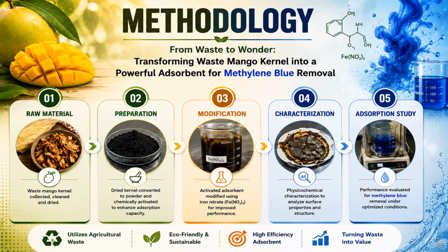Let us now sneak into the methodology. Waste mango kernel was collected, cleaned and dried. Later, it was ground and sieved through a 500 micrometer mesh and dried at 60 degrees Celsius for 1 day. Then, the powder was heated at 500 degrees Celsius for only 30 minutes, yielding the biochar. To prepare iron-decorated biochar, the prepared biochar was mixed with iron nitrate in a 1:2 mass ratio, and then, after the addition of sodium hydroxide, the iron mango kernel biochar was filtered, rinsed and dried at 105 degrees Celsius for 24 hours, and the samples were subjected to characterization such as FTIR, SEM and XRD analysis, and later was evaluated for methylene blue removal.